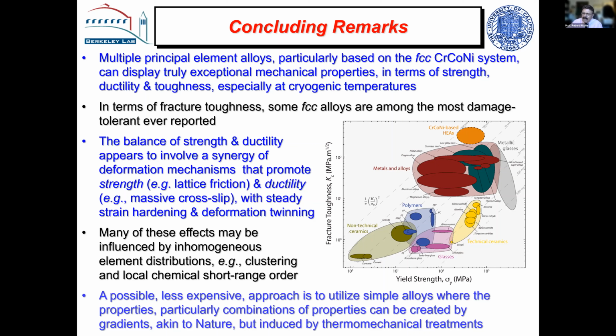So the keys are there. We don't have it put together perfectly yet, but that's exactly what we think, that local order is sort of instrumental in generating this remarkable sequence of deformation. You can't do it at the grain size level, so you're doing it at the atomistic level, which is a kind of intriguing thought. But whether you can control that is another issue. Manipulating local order may not be possible.